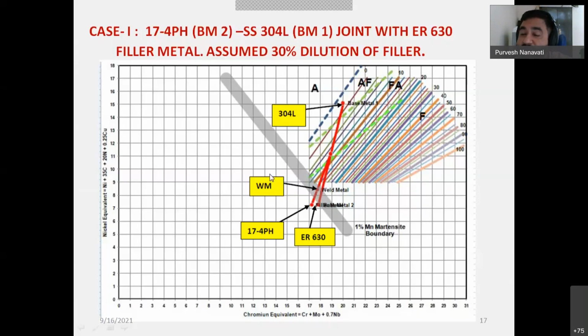So you can definitely say that it is not without risk, right? This analysis shows that the weld joint is not without risk. It means there will be every chance of martensite development in the heat affected zone, and there will be cracking, right? Because of the thermal cycle. So it's a theoretical estimation of weldability, right? And these A, AF, FA, F are showing different solidification modes, right?